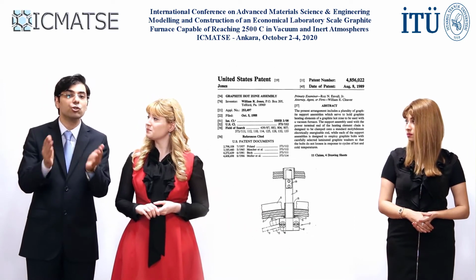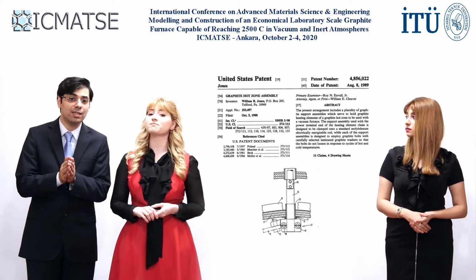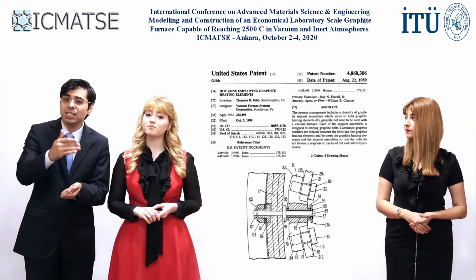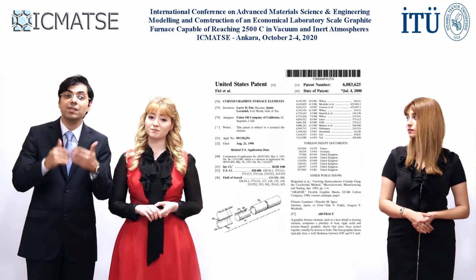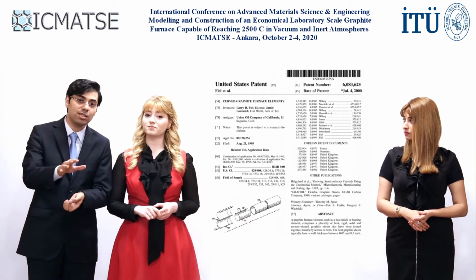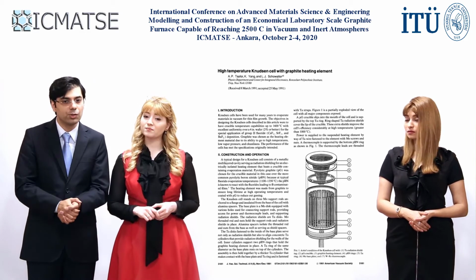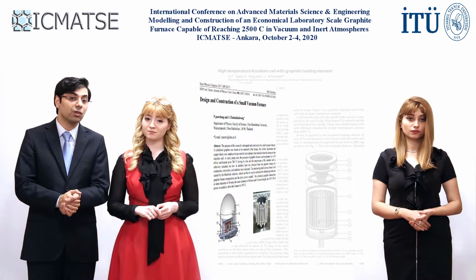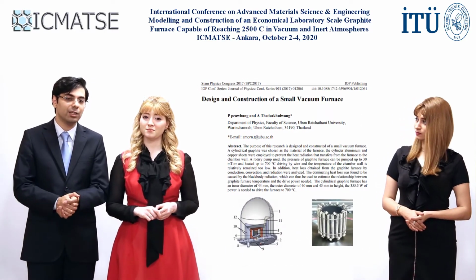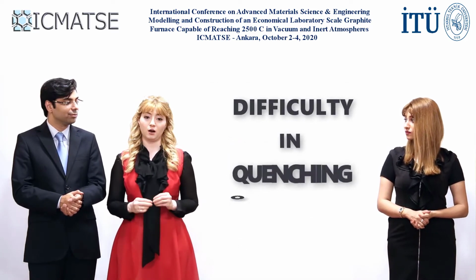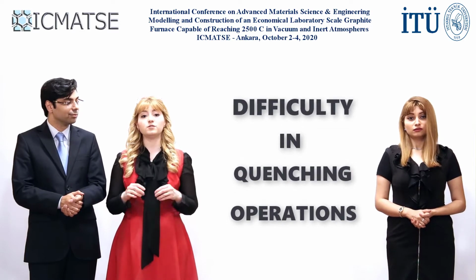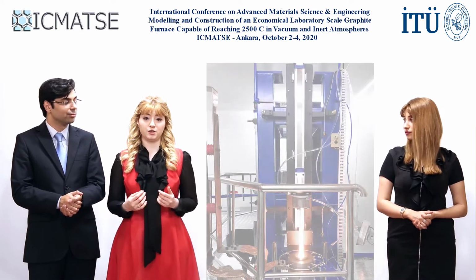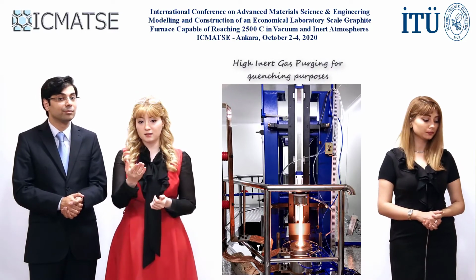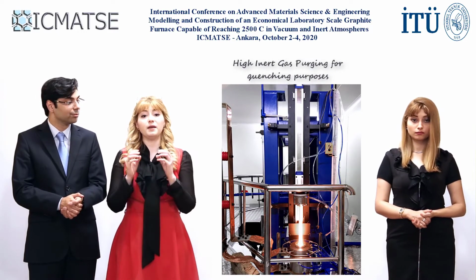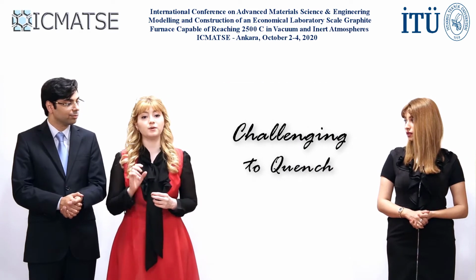It is noteworthy that the majority of available designs require utilization of step-down transformers with ampere ratings of over 1000 amps, thus increasing the primary cost of the furnace as well as the cost associated with replacing and repairing of the hot zone due to the geometrical setup of the graphite heating elements used in the available designs. An additional problem with graphite furnaces is the difficulty in quenching operations, which tends to be solved through rather operationally inconvenient procedures, such as high inert gas purging as in the case of silica fiber drawing furnaces, making it rather challenging to quench a sample in vacuum.